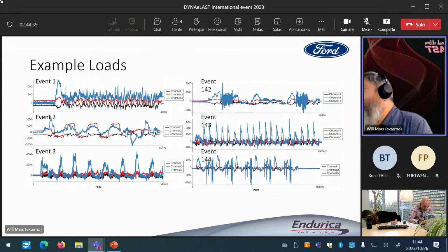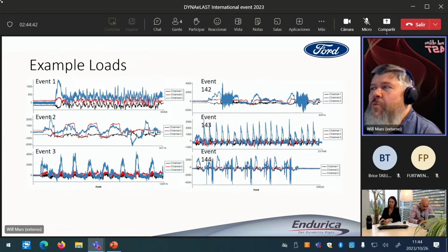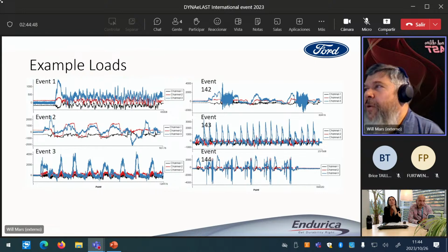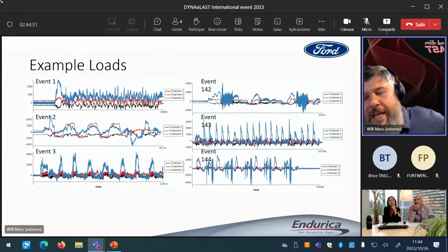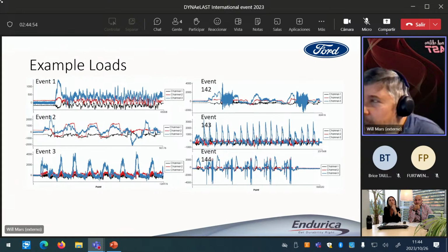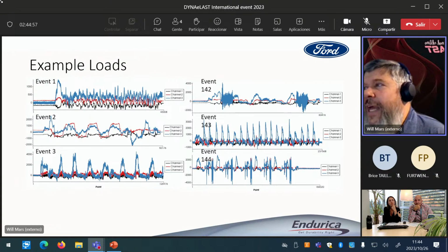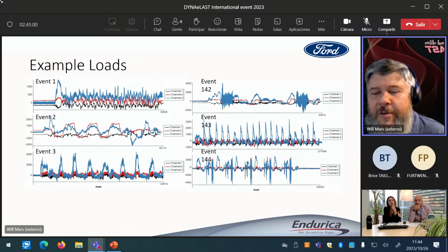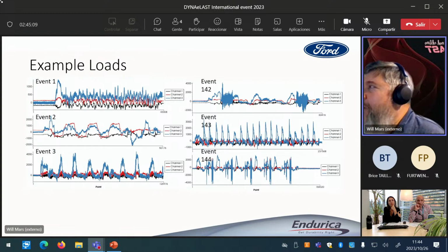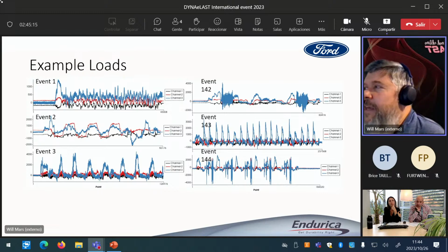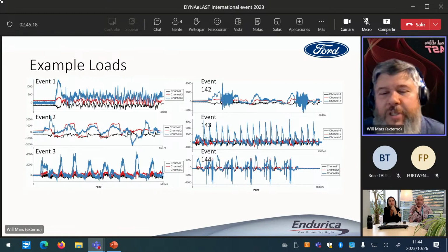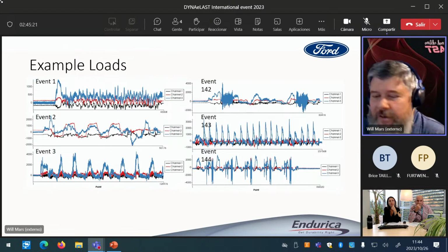Another thing that Ford gave us was the recordings of each of the 144 different events. And what you're looking at here are examples of 6 out of those 144. You can see that they vary in length. Some of them are very short events, maybe a wheel impact. Some of them are longer events. But like I say, they're recorded at about 1,000 hertz, and they basically define the force X, Y, and Z force inputs to the mount as a function of time.